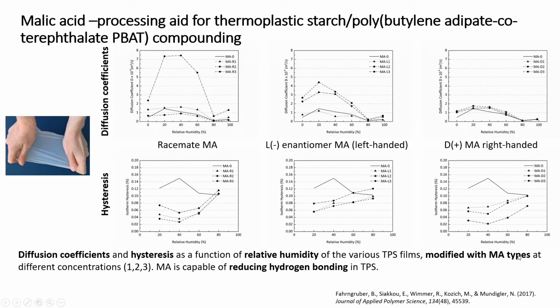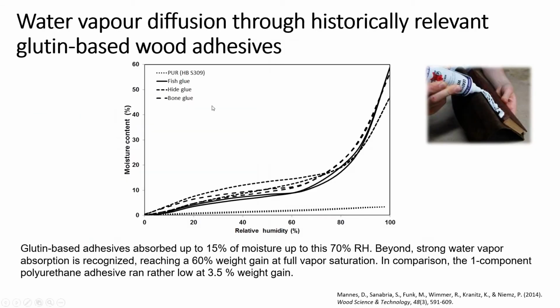And with the MA types, the malic acid additive contents and types that we have added, we have seen overall that MA is capable of reducing hydrogen bonding. You see here when you go from MAR1 to 3, so there's a higher content at the number 3 type, that the diffusion coefficients are going down in this case, and you see the hysteresis is changing as well. So this was valuable information for the industry in the discussion of what they want to change in future, because that market is picking up greatly at the moment with the biopolymers.